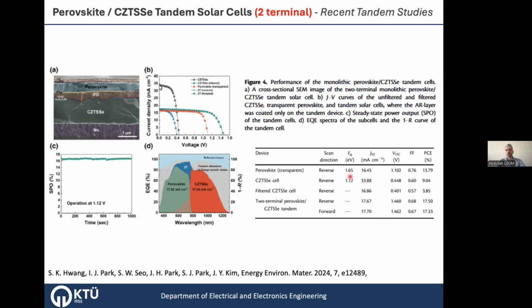Again, you see that this is the standalone CZTS selenide solar cell with the high current, but the limiting current here is this transparent perovskite, you see, and the tandem device is limited in this current, but you can add the voltage because it's serially connected, and you can have efficiencies like 17.6% in this device.